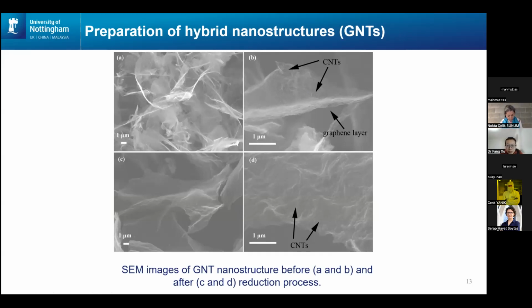Okay, so we reduce the nanostructure in a hydrogen environment in a tube furnace. After that, we can see those thin layered structures have been retained, and we can observe carbon nanotubes as well, which means agglomeration didn't happen during the reduction process, and we indeed achieved the reduced graphene oxide and carbon nanotube structure. But how well the graphene oxide has been reduced, we will have a look as well.